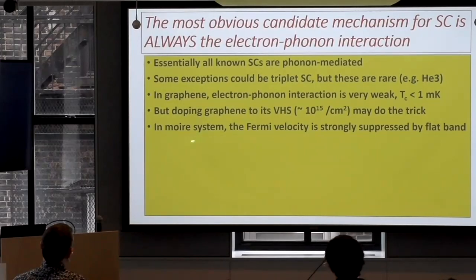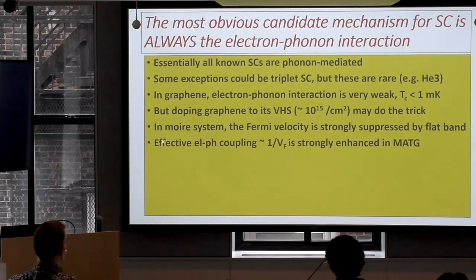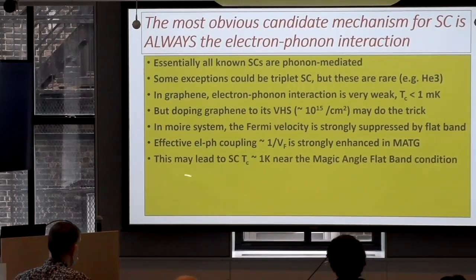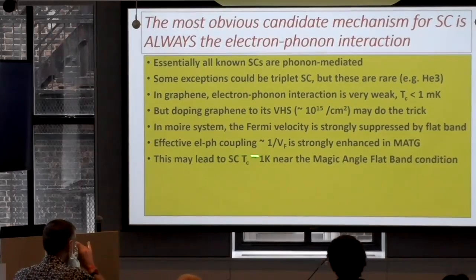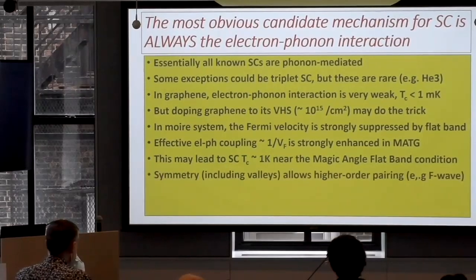I said, oh, it's very simple. Fermi velocity is strongly suppressed. That increases the effective electron-phonon coupling because that goes into the denominator of the effective coupling. So if you have a Fermi velocity factor of 100 lower, electron-phonon coupling will be a factor of 100 higher. And in fact, Fermi velocity is zero at the point where you have this magic angle, then this coupling is going to go to infinity. Of course, the theory would not apply there. If you just do a BCS formula, this will immediately give you a Tc of 1 K. This is the basic idea.